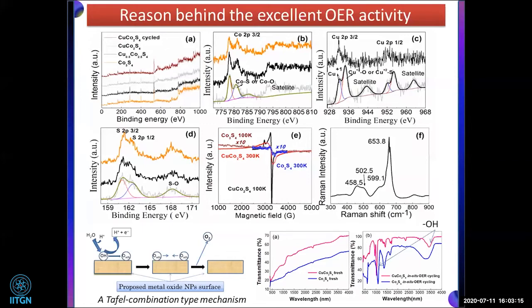Another thing, if you can see, this is a pseudo in situ OER FTIR. You can see this pink one. This is the copper cobalt sulfide. There is OH, a medium band and a strong band, which is absent in the case of Co3S4. So when we introduce copper into the lattice, it gives this adsorption. This is when we are doing the OER reaction. So it shows that because of the copper, we have more adsorption of OH groups there, and finally it gives a Tafel combination type of mechanism, as we can see in this.